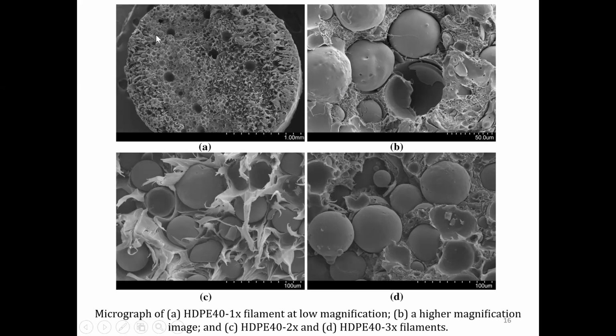This is one-time extruded, 1x, meaning we have extruded one time, with a higher magnification of this in here, then this is 2-time extruded, and this is the 3-time extruded one. What that means is we extruded one time, and then we checked the recyclability potential of these filaments. We chopped these 1-time extruded filaments and extruded again, and that is 2-time extruded. Then again we chopped this 2-time extruded filament and extruded again, that is the 3-time extruded filament. Here HDPE40 means 40 weight % of fly ash cenospheres, which are hollow microballoons. You can see here a broken one, infused in high density polyethylene and extruded multiple times.